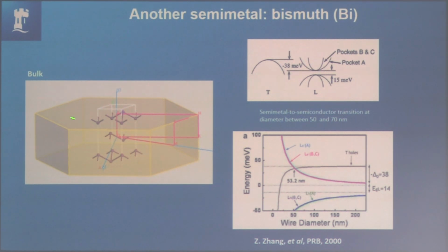You could even think of it as a 2D material because it forms layers with one atom at the base, puckered to 3 atoms at the top, which are in turn bonding to 3 atoms down. So it's very much like a typical 2D material. And in this 1-1-1 hexagonal direction, it really does look like a layered 2D material with weak interactions. It's really exciting for electronics because it has the highest mobility of any elemental material, by far.